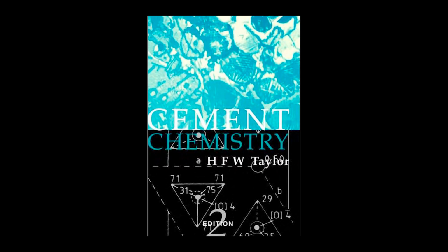And that brings us to the end of our deep dive into Portland cement chemistry. We began by demystifying the essential shorthand, the difference between C3S and C2S. We moved through the manufacturing process, recognizing that the difference between a high-quality cement and a failed batch is often measured in the composition of a low-temperature sulfate melt, or just a few minutes of accelerated cooling.